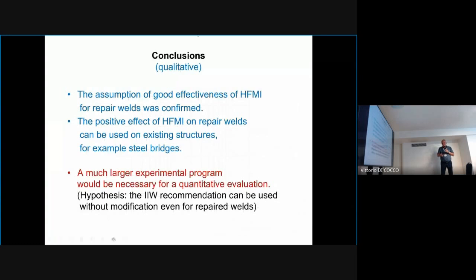I think that we can give the conclusions from the qualitative point of view. We can say that our work has confirmed that HFMI is a very effective method for improving repair welds, and it means it can be used on existing structures, for example, steel bridges. For quantitative description, we need a much larger experimental program, I think, to agree or disagree that the IIW recommendation can be used without any changes for repair welds as for the initial welds.